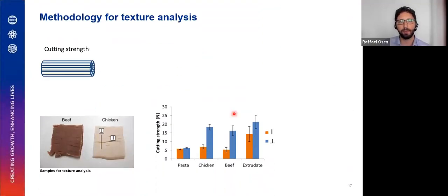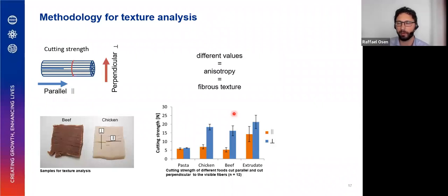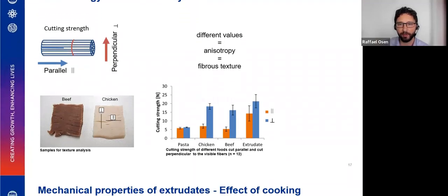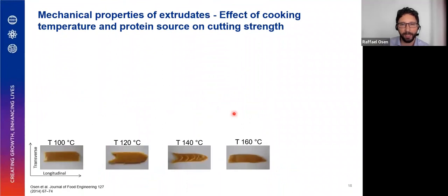So the method to test for the texture properties is very simple. It's testing the cutting strength using a texture analyzer in length and crosswise directions, whereas similar values are indicated for a uniform structure, and different texture values in length and crosswise directions are indicated for a fibrous structure.